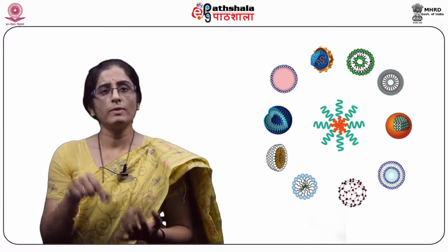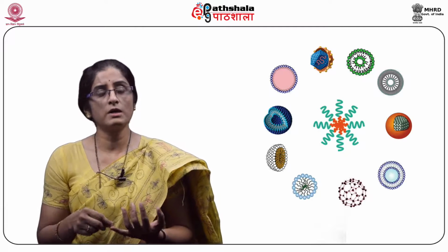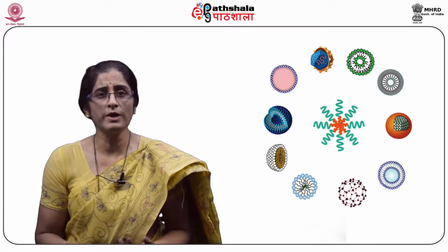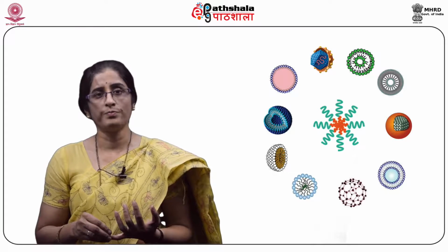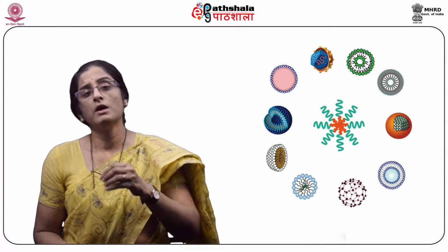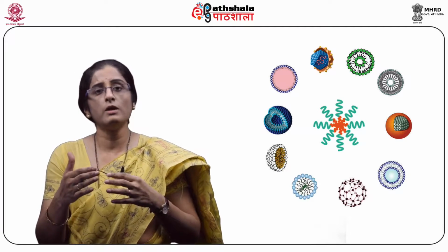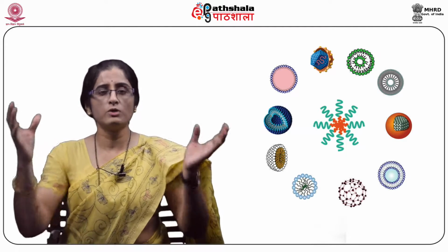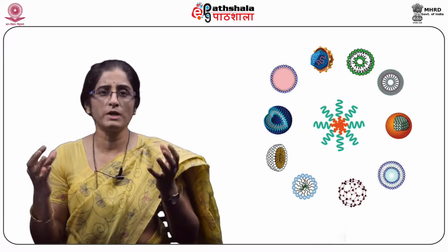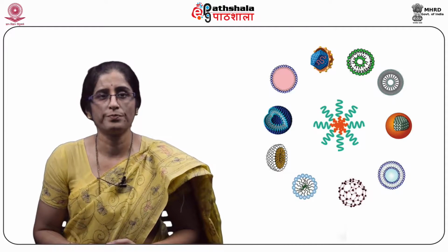And this disc atomizer generally rotates at a very high speed like 50,000 RPM. And when one drop of the slurry is put on this disc atomizer, it will break that particular droplet into several, or 1,000, droplets having size in the nano range.